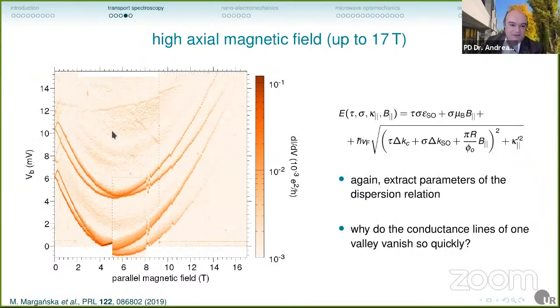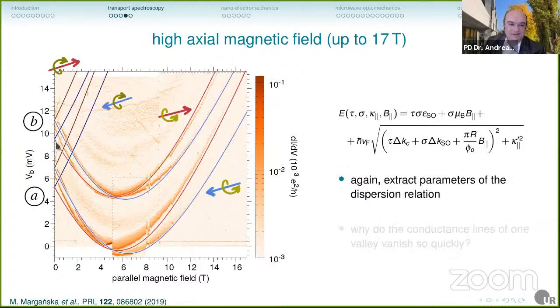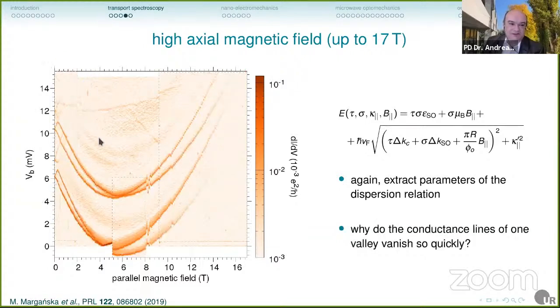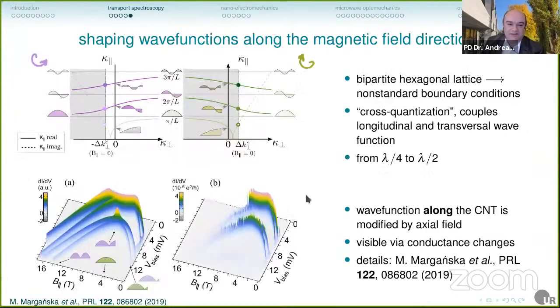For example, one puzzling detail is why are these lines that go up vanishing so quickly? You can see this is basically one valley. This is another one. And here the lines, the conductance immediately disappears. And this was something that we looked at some time ago. So basically there's a special effect due to the bipartite hexagonal lattice of the graphene. You get a non-standard boundary condition, a non-standard quantization condition for the trapped wave functions.